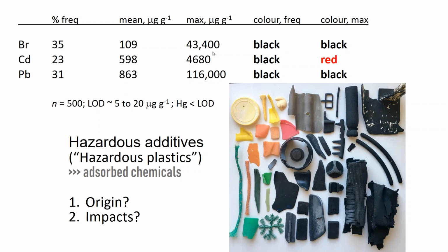The other thing that's interesting is that when we look at the colours, we find that black stands out. In other words, the most frequent colour in which we find these chemicals in beached plastic is black, and the highest levels, certainly of bromine and lead, are nearly always black. Cadmium in this case was red. And over on the right hand side, on this image here, these are images of some of the samples which exceed the RoHS, in other words, they exceed the legal limits for cadmium, lead, bromine in electronic plastic. Now, clearly these aren't electronic plastics, but nevertheless they are non-compliant with respect to legislation which is, well, I suppose it's the nearest legislation you could find to this sort of material.